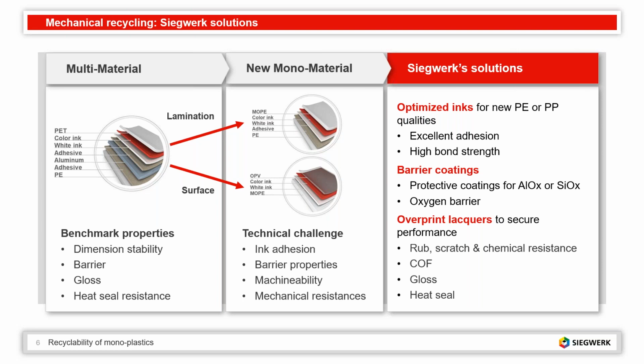We are also working on oxygen barrier coating, and we're not too far away from a commercial solution there. For now, you might want to work with Alox or SiOx coated monoolefin films. When you do this, you will probably notice that they can be very brittle because the olefin film is still more flexible than the PET that you've used in the past. So it's difficult to work with, and therefore we have developed protective coatings for these Alox and SiOx films to make it a little easier to work with them.